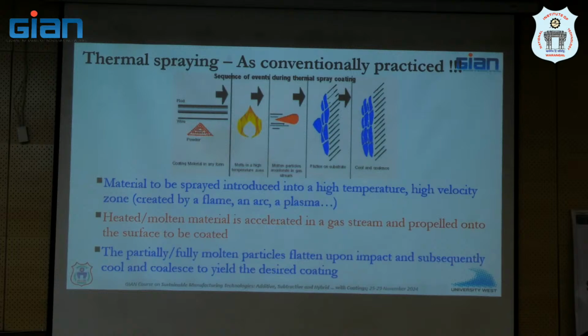And why do you want it at high velocity? Because these are all mechanically anchored coatings, yeah? So before you do this coating, you roughen the substrate by grit blasting, right? So why do you want high velocity? So that these splats, because of the roughness, can stick properly, correct? If it's a very smooth surface, it doesn't stick. If it is not fully molten also, it doesn't stick, correct?